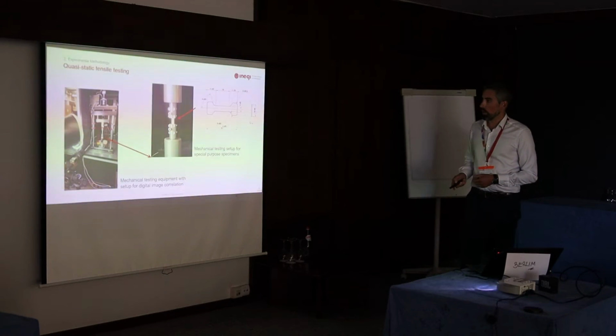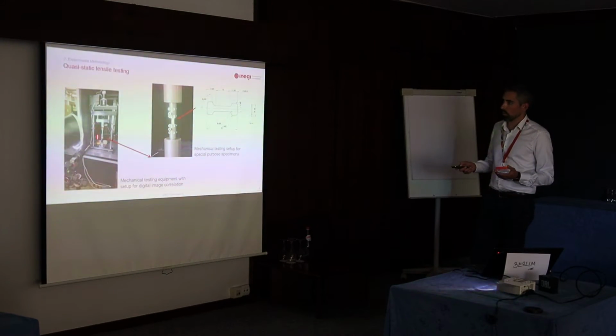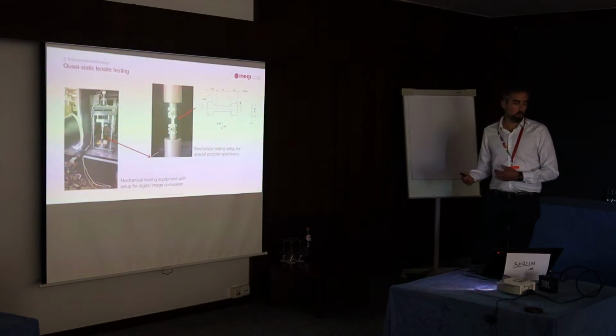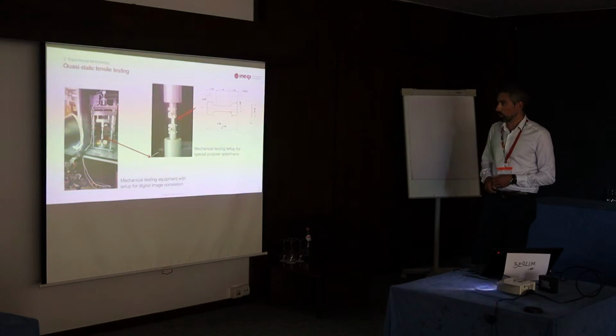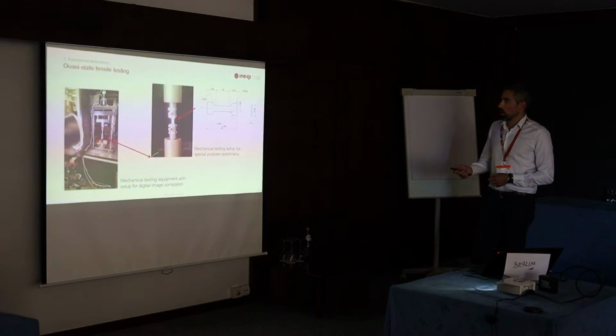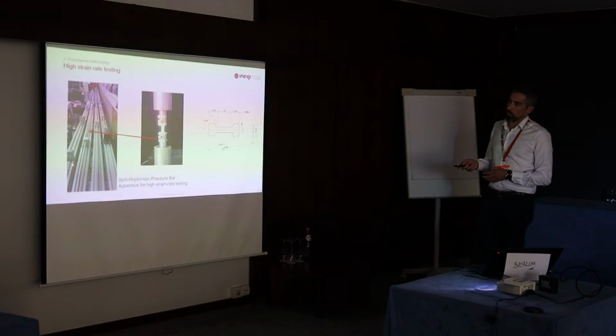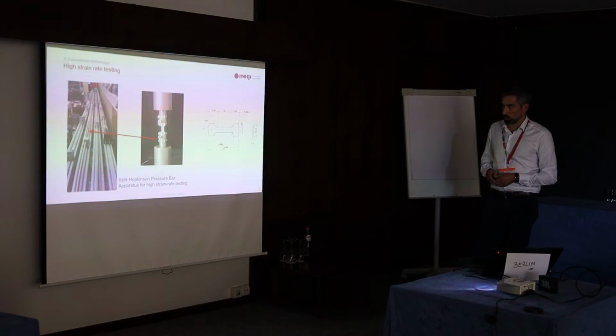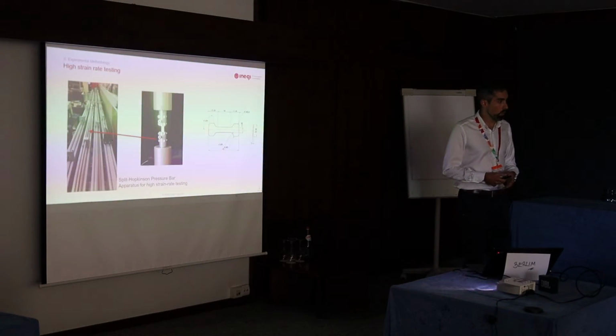So here is the setup for quasi-static, which would be tested with the same setup as is used in the split Hopkinson bar. Nothing special. And here is the bar. For example, here it's an apparatus which has 4 bars, 2 in compression and 2 in tension. And the bar to test this specimen was made of titanium.